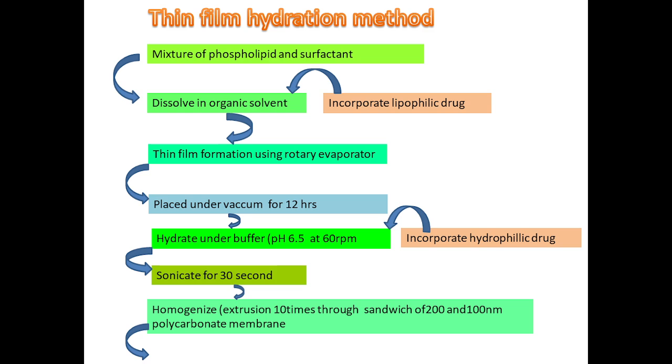So the first step is phospholipid and surfactant, that is dissolved in organic solvent. At that time the lipophilic drug is incorporated. Then thin film formation by evaporation of solvent using rotary evaporator. Then place under the vacuum for 12 hours.